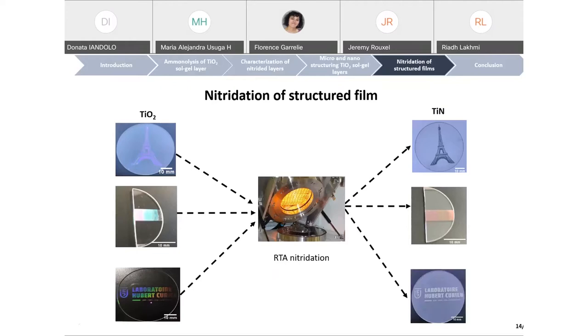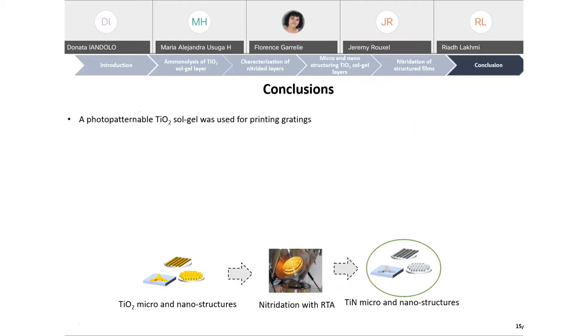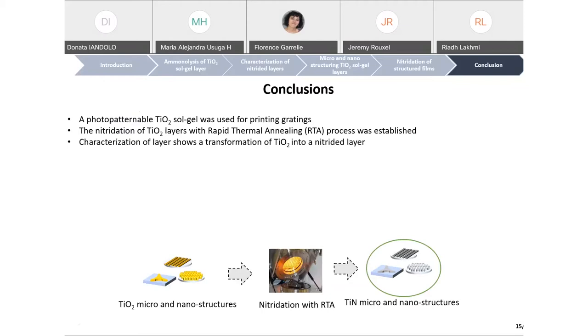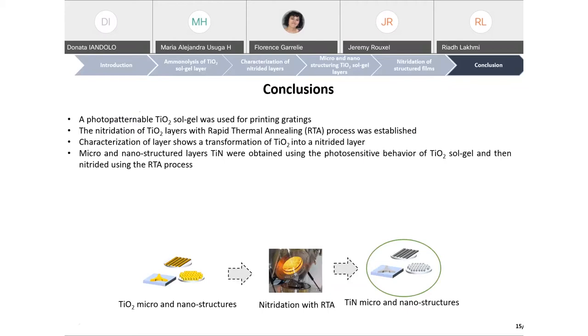It is demonstrated that it's an easy technique to realize titanium nitride micro nanostructures using a photopatternable sol-gel and a rapid thermal ammonolysis process. From the conclusion of this work, a photopatternable titanium dioxide sol-gel was used to print a grating. The nitridation of the titanium dioxide layer with the rapid thermal annealing process was established. The characterization of the layer shows a transformation of titanium dioxide into a nitride layer. The titanium nitride micro nanostructure layers were obtained using the photosensitive behavior of titanium dioxide gel and then nitrided using